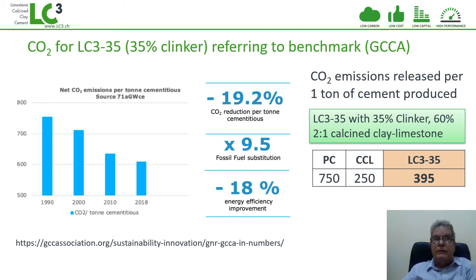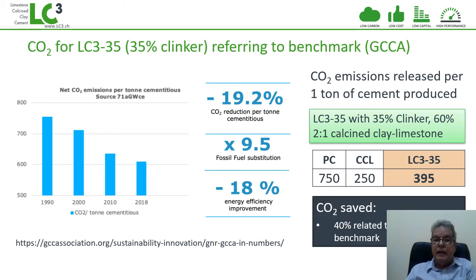A similar case for LC3 35, which we propose for bags, I mean cement for less compromised applications, where we have the figure of 395 kilograms of CO2 per ton of LC3. And here we can compare with the benchmark from the Global Cement and Concrete Association, which is around 620. And we see that even in this case, we're able to save 40% of carbon emissions, meaning we're making a significant contribution to reducing carbon emissions.